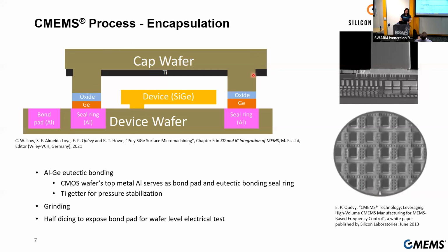The process for the cap wafer is very straightforward. We first do a deep etch into the silicon, and then we generate that cavity. And then we do a titanium deposition. The titanium serves as the getter material to absorb outgassing. And then on the sealing, we do oxide deposition as electrical isolation. And then the germanium is deposited. The germanium will be eutectically bonded to the aluminum, and we create a hermetic seal for the resonator. After bonding, the wafer will continue with grinding, so it gets thinner.